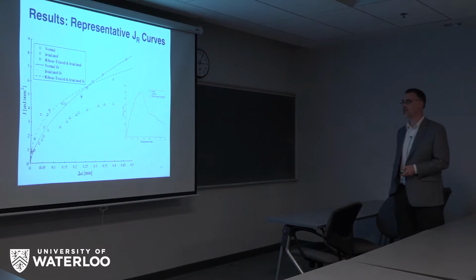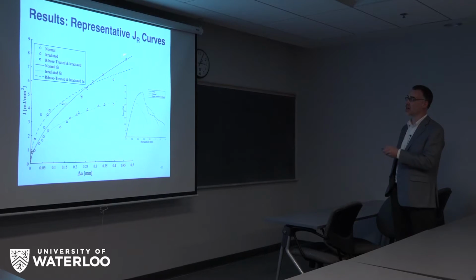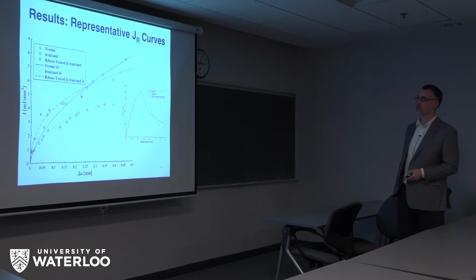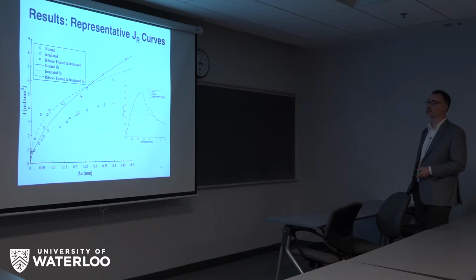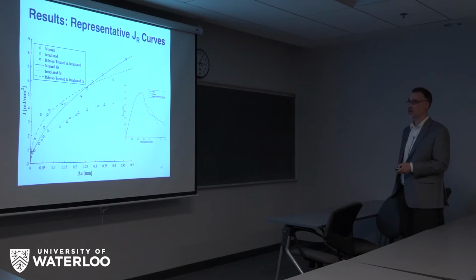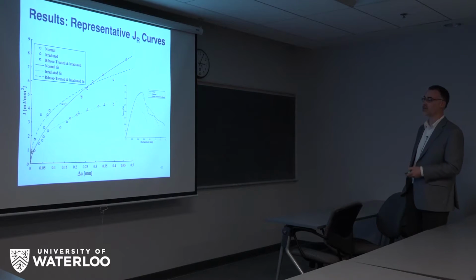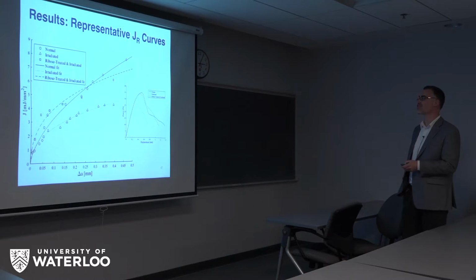And here are some representative curves. So J versus crack growth. These are the force versus load line displacement curves if you're interested in those. But as we expected, we have the normal bone in the solid line. The dotted line is irradiated, and then the circles and dashed line, that's the ribose pretreated and irradiated. So you can see the protective effect over a range of crack growth.